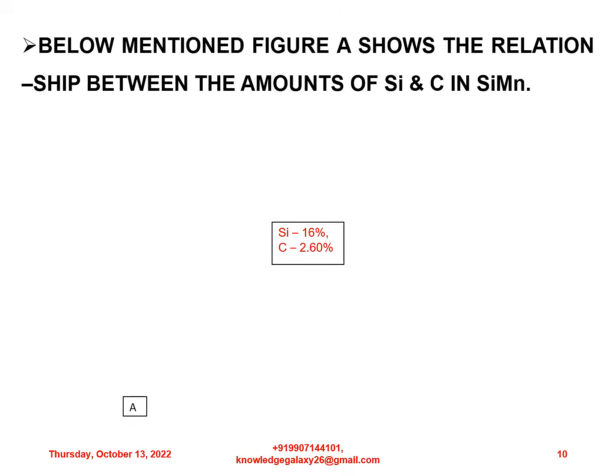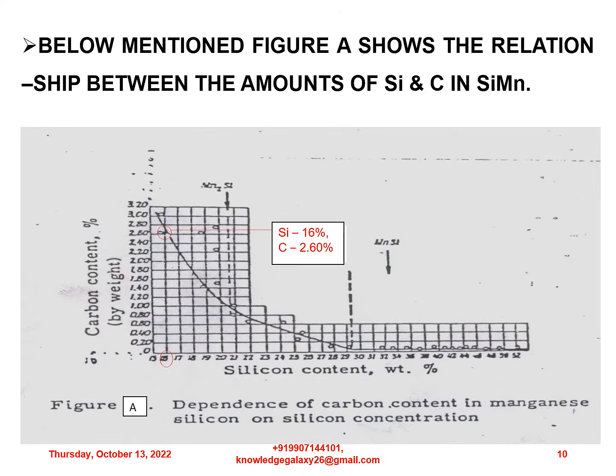This graph shows the relationship between silicon and carbon in silicomanganese. As can be seen, the optimum silicon content, that is 16%, carries carbon up to 2.6% maximum.